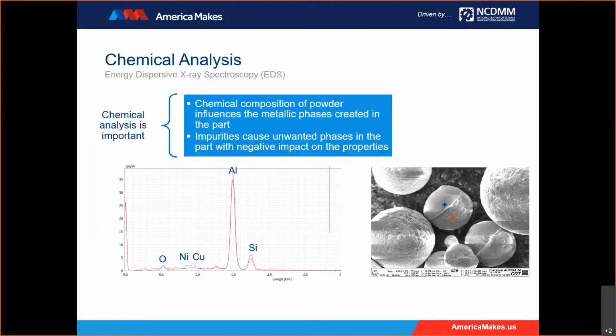And why would we do this? Well, we do this because having homogeneous powder is important for the AM printing process. Because during printing, we're creating the mechanical properties as we build. So we don't want variation in the raw material. The existence of any kind of contamination, such as oxide particles, will affect the mechanical properties and potentially induce weakness in the part. And we know that spatter, for example, has a different chemical composition than initial powder due to the loss of low melting point elements. For example, in Ti-6-4, there's reduction of aluminum.